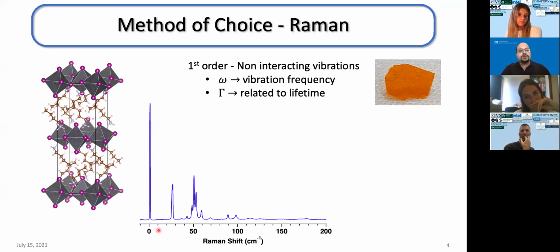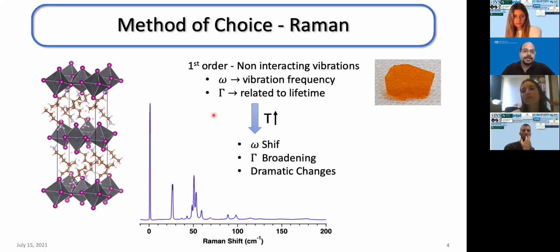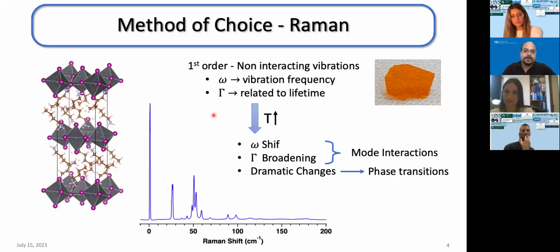Now, to first order, we assume that each peak here is a standalone vibration. They don't interact at all. Every peak has a frequency and some full width at half max, denoted by this gamma here, which is related to the lifetime of the phonon, of the vibration. Now, as we increase temperature, in first order we would expect to see nothing because there's no temperature dependence. But in real life, we see shifts of the frequencies and broadening of peaks, which are related to mode interaction, vibrations interacting with one another, affecting one another. And sometimes we even see dramatic changes in the spectra, which are related to phase transitions.